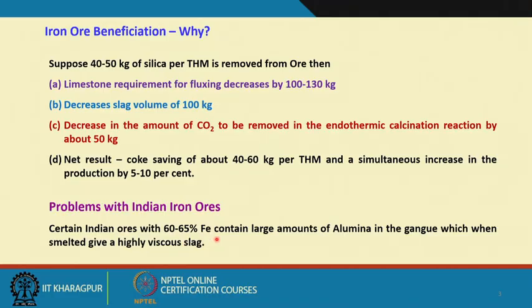But still we are saying that there are problems with Indian iron ores. What is that problem? Certain Indian iron ores with 60 to 65% Fe contain large amounts of alumina in the gangue, which when smelted give a highly viscous slag. Although the iron content is very good, you have got alumina, and this alumina imposes viscosity related issues with your slag. So, if the flowability of the molten slag is affected, then you cannot take it out at a rate commensurate with the rate of its production inside the blast furnace. So, what will happen? There will be an accumulation of this slag, and your blast furnace productivity will decrease.